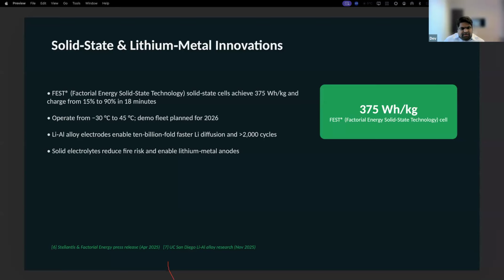So this is another selling point when you have thousands of cycles of a battery, which means it would outlive a typical application of an electronic or electrical device, including electric cars. Compared to the other components, the battery lives longer, so it could be easily harvested for further use later on. The types of solid electrolytes that are being used are sulfide based, which have high ionic conductivity but are sensitive to air, oxide based, which is stable but brittle, and polymer based, which are flexible but have lower conductivity. So these are some of the challenges which the researchers are going through at the moment.